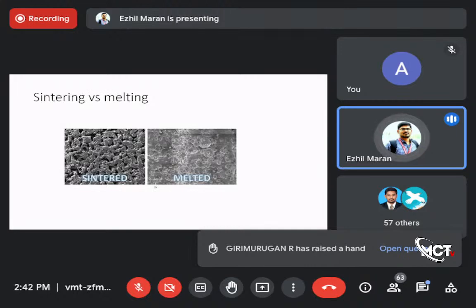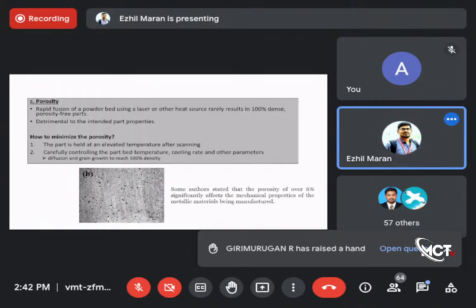So this is the layer sintering versus melting. If it is sintered, the part contains a lot of porosity, and if it is melted, no such porosity is visible. So melting is also a very good way to 3D print rather than sintering. But for some applications, sintering is the best. So this is the porous structure, I mean, unorganized porosity material due to the thermal process. As I said, it is a raw bed of powder. So a 100% dense product is not possible by using additive manufacturing. Maybe 90% or 95% density can be attained even with the proper processing parameters. Otherwise, 100% density may not be attained.